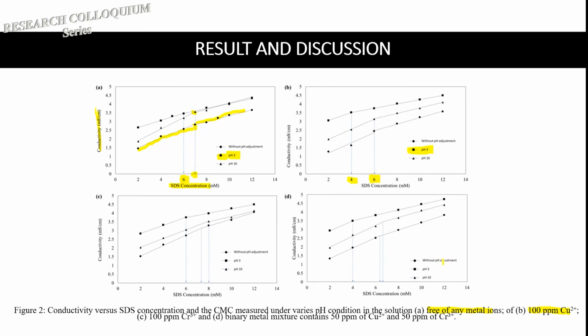It seems like the presence of Cu can serve as a bridge to link all the SDS molecules together. In other words, the presence of Cu enables the SDS micelles to form at even lower concentrations. But on the other hand, if we put in 100 ppm of chromium, disappointingly all those CMCs still remain almost the same compared to the first system, 6 millimolar compared to the 7 and the 8. So it seems like the presence of chromium does not contribute to the CMC formation.